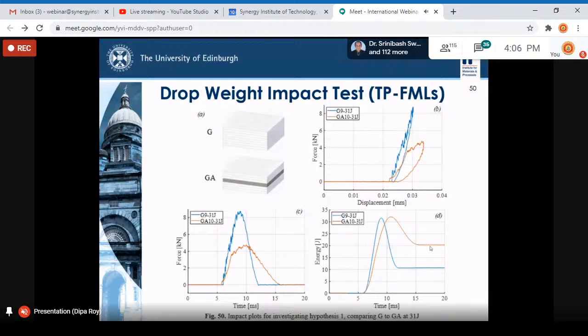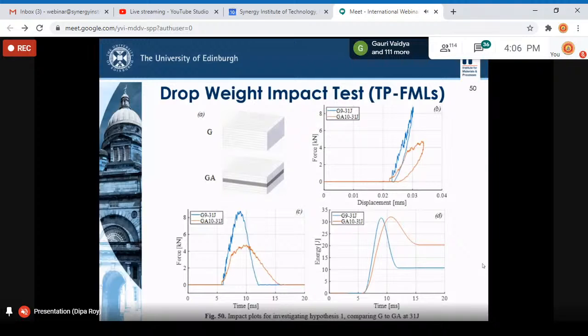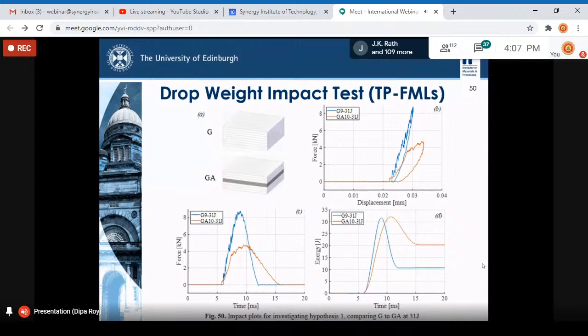It means that if a hybrid laminate like this undergoes a sudden impact, it is able to absorb a lot more energy. That energy is being absorbed by this interbonded overall composite. The aluminum alloy itself is a highly ductile material, so it can undergo a lot of deformation and absorb energy. This kind of interfacial debonding and absorption of energy by the aluminum alloy can prevent perforation of the overall composite structure. So in that way, this can be highly advantageous. We can have a lot more impact resistance from these kinds of combinations.